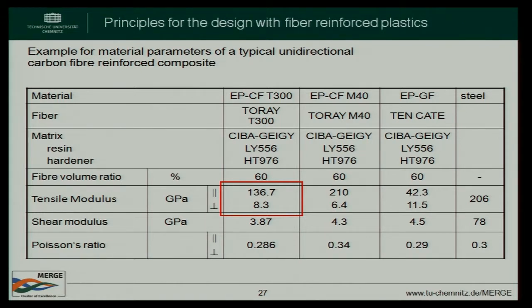And now you see the tensile modulus in fiber direction and perpendicular. So this is a huge difference. You have more or less no stiffness perpendicular to the fibers, a huge stiffness in fiber direction. Okay? So designing with fiber reinforced plastics, it depends. You have a lot of variations where you can adapt the specifications of the material to the load. First is the fiber volume content, which fiber you use, which matrix you are using, and then you have all these resulting different properties. So this makes it so difficult in engineering, yeah? Engineering, calculation and design with fiber reinforced plastics is much more complicated than design with, let's say, classical steel.